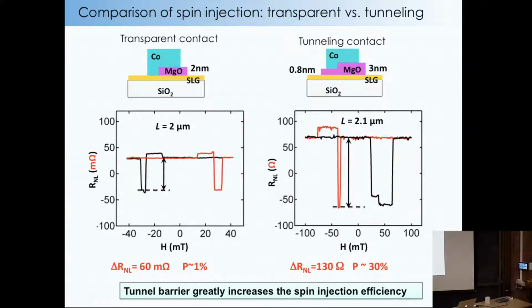This was a very nice advance, and the numbers that came out of this work were plugged into all these magnetologic devices, saying this should be the best material. Although we don't get this all the time. We can routinely get 50 ohms or so, but 130 was the biggest we've gotten. So this was expected, and that's what we saw.